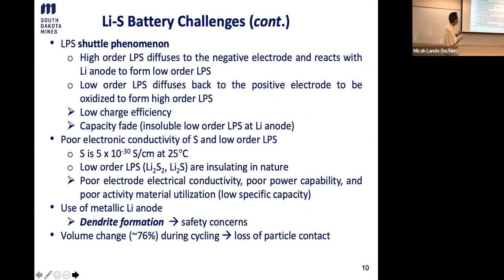So imagine you charge the cell, right? When you charge the cell, you want to oxidize the sulfide back to its original sulfur, and then you can't do that because once you reduce this higher order to lower order, you have more higher order due to the shuttle. So you're kind of going back and forth. You're just doing nothing about your charge. You can't charge it. So that's a very, very low charge efficiency. So that's called the shuttle phenomenon, which you don't want.